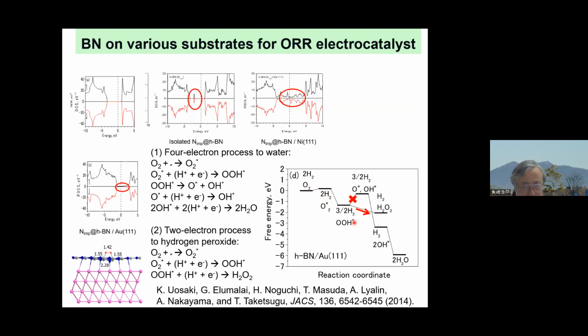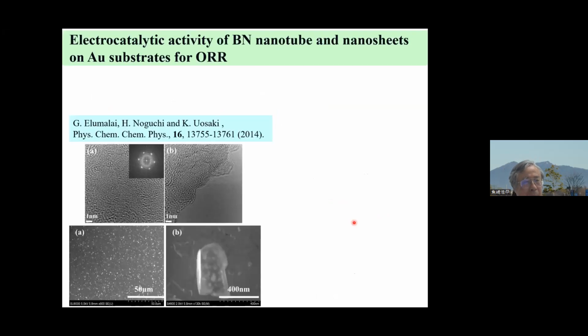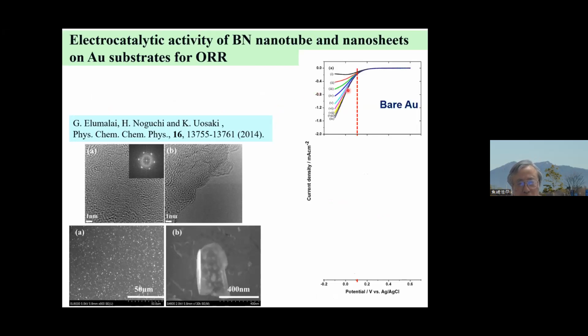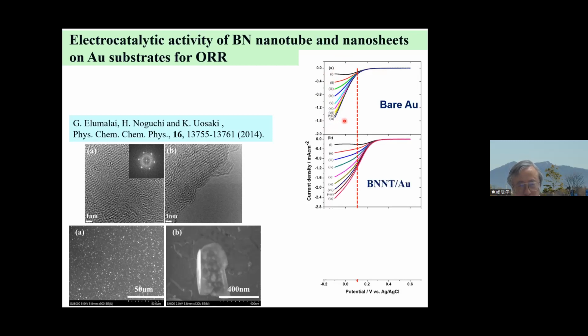So we carried out experiments. We used a gold 111 substrate. Then we carried out rotating disk electrode measurements. This is the oxygen reduction. The theoretical oxygen reduction potential is far positive, but in the case of bare gold, this is very bad. The electrode is rotated, so the oxygen supply is controlled. Then first we used boron nitride nanotube. It looks better. It's shifted to positive.